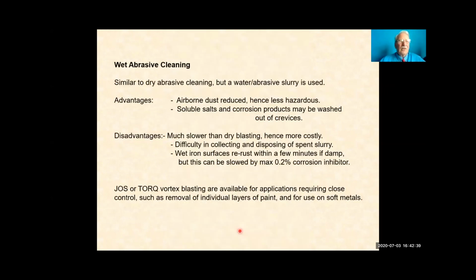Now, one of the problems I showed you was that with dry abrasive cleaning, it blows dust everywhere and you can't see what's going on. So why don't we use a little bit of moisture with it to control the dust, so it makes it less hazardous. It also means that soluble salts and corrosion products may be washed out of crevices. On the other hand, they might be washed into the crevices, so you never quite know. It depends on the metalwork.